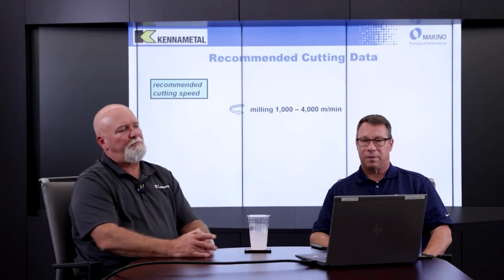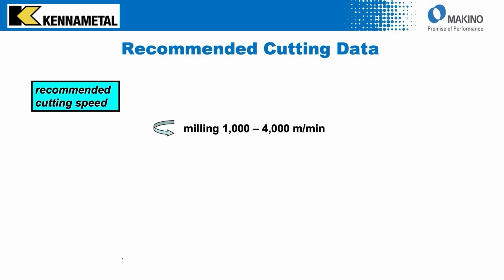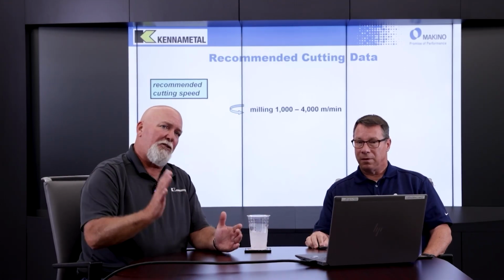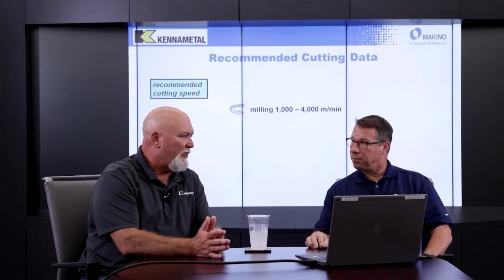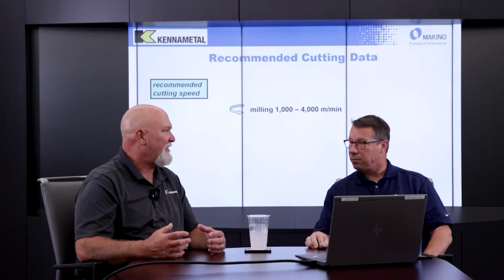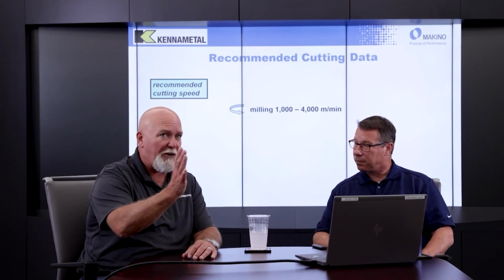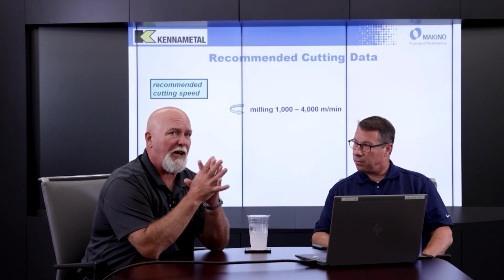Yeah, so we see a lot of milling in the applications that we run, and when we talk milling, generally we can run between 1,000 meters and 4,000 meters a minute speed-wise, and these are aluminum parameters that I'm giving you. The range there is based on the silicon content and how abrasive the material is, or if we're cubing, sometimes there's green sand castings with a lot of scale on the outside. Sometimes we'll run a little slower in that range to help out with tool life there, but that's the kind of range we can run, and it's a pretty big range, honestly.